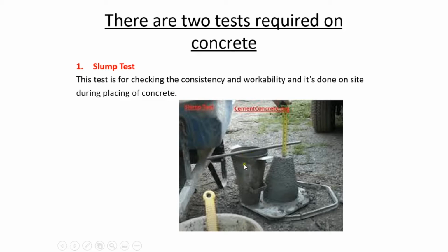Once the cone is full, you turn it upside down, and you'll have this type of concrete mold. By looking at the slump difference, if it is a dry concrete, the slump must be at a maximum of 75 millimeters. If it is a wet concrete, the slump must be more than 150 millimeters.